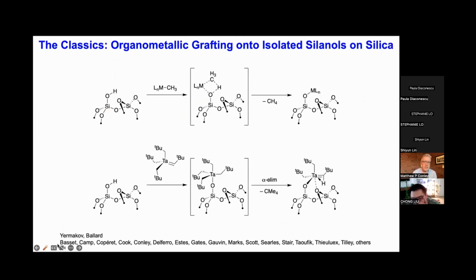So these are just some of the names of the people that are involved in this field. It really all started with Yermakov and Ballard, who were looking at organometallic grafting reactions to mimic the active sites for Ziegler-Natta olefin polymerization catalysts. So if you take your silica 700, react with some sort of organometallic, you generate this sigma bond metathesis type transition state where you're transferring a proton to the organometallic, and the metal is then making a metal oxygen bond to generate your well-defined site. If you have